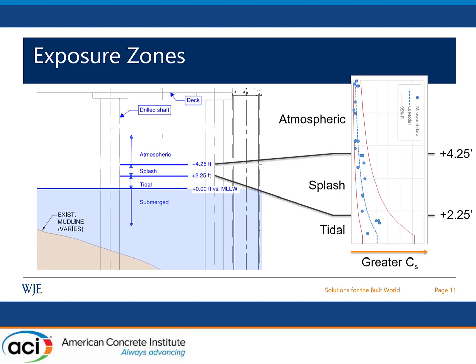And based on our results, we found strong correlation between the estimated surface chloride concentration and the corresponding height above mean low water level at which the cores were drilled. So on the right here, I'm showing the figure of the surface chloride concentration estimated for the different cores. And showing with the height above the mean low water, so with the different exposure zones. And we use this correlation for our modeling. So we use the power model fit for the surface chloride concentration with height.